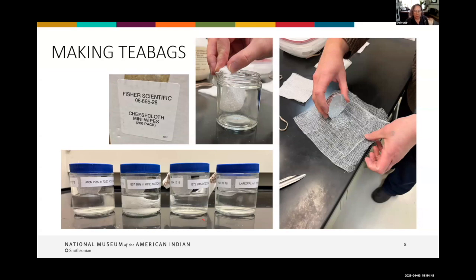And the fiddly part is getting the bags to just touch the top of the solvent without being completely submerged. This helps the resin to just kind of be drawn into the solvent instead of, if you just put it all in one time, you could just get a big clump of resin. And I suppose eventually it would dissolve, but it might take longer and not be as clean. But anyway, this is the way that we did it. And once the bag sits right on top of the solvent, we flatten and smooth the gauze along the top of the jar so that the lid can screw on tightly.